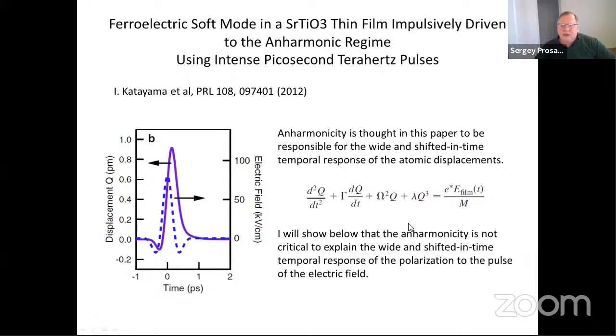As introduction, let me first show maybe one of the first papers, which was experimental. The dashed line is the electric pulse, and the solid line is the displacements of the atoms in strontium titanate thin films. Time is in picoseconds. First you see that the displacement curve is shifted with respect to the electric signal curve, and also it is wider than the electric pulse.